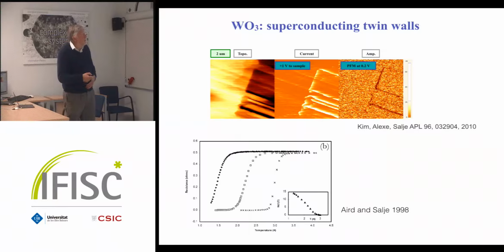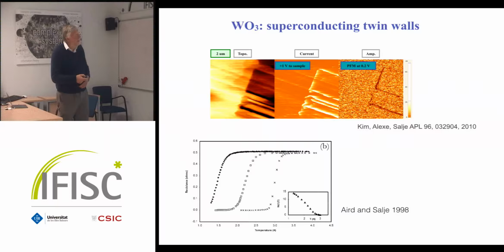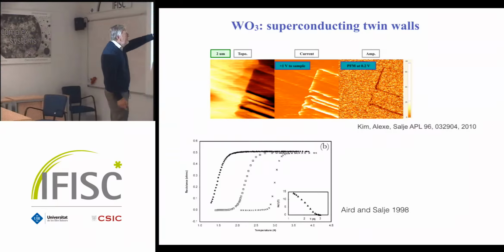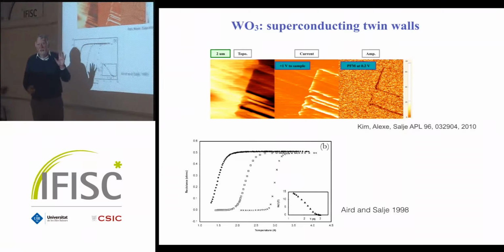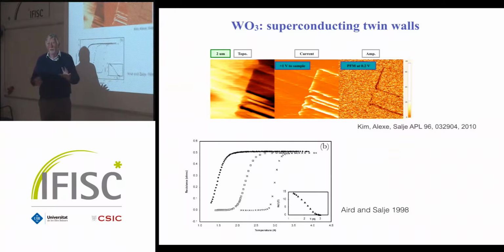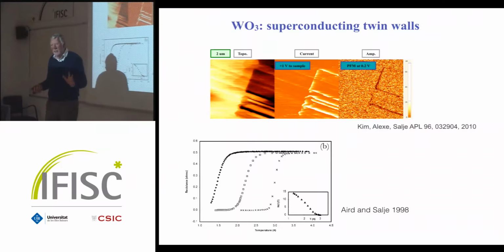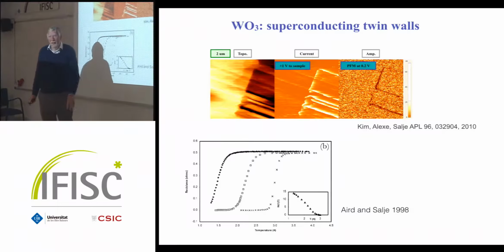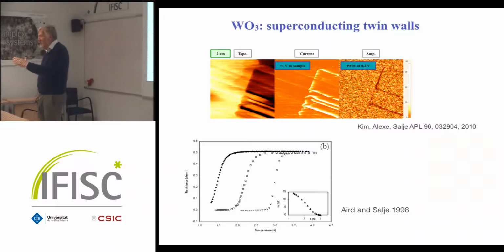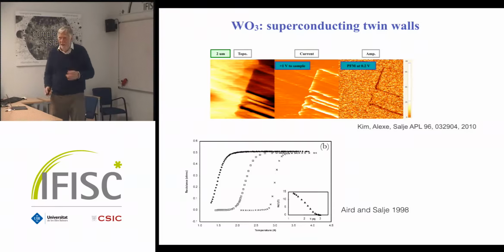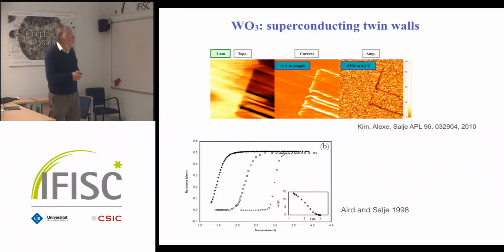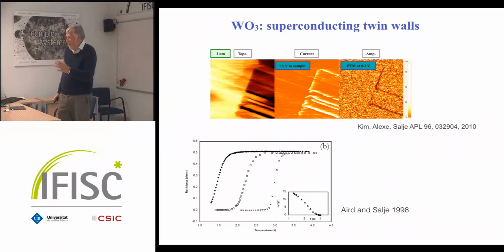So here you can see that in the PFM signal you have black for the boundary and for the current you have white. Now what is very interesting is that this white is really very white. The conductivity on tungsten oxide is a good insulator. Think of sodium chloride, really a good insulator. These conducting areas are like a metal. So you have like metal planes in an insulating matrix. But it gets better. When you go to low temperature at 3 Kelvin, these areas become superconducting. So now you have superconducting planes in insulating material. Right? So that's quite spectacular.